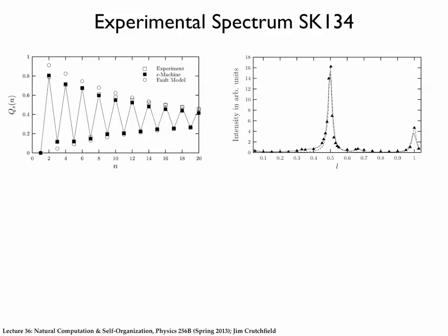You know, not perfect. Over here, starting roughly in here or so, you can see that we're kind of missing it, that our description is predicting smaller oscillations as it approaches an asymptotic value, but still here, it's not too bad. The fault model is clearly not as good.